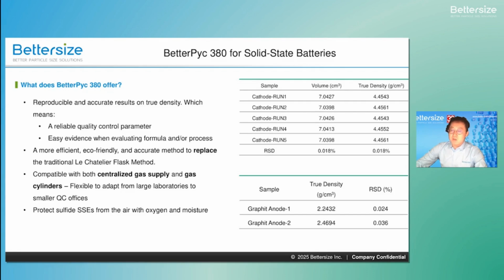Furthermore, specifically for sulfide SSEs, this system allows us to measure volume without exposure to moisture or oxygen, ensuring the chemical integrity of your sample remains synonymous with your data integrity.